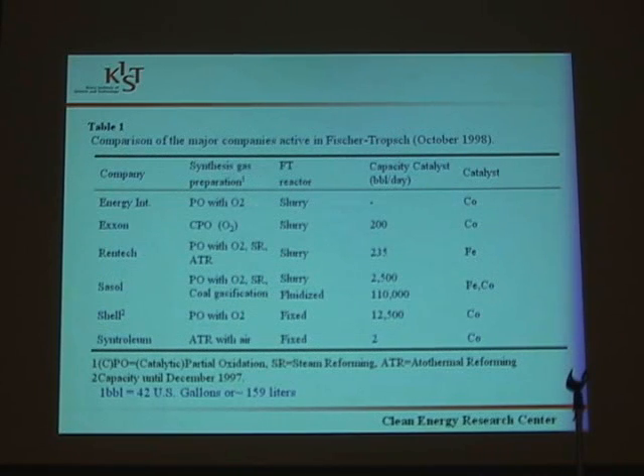Up till now, major companies are already using some catalysts for Fischer-Tropsch synthesis, as given in this table. Energy International is using partial oxidation. They are preparing syngas using partial oxidation with oxygen, using a slurry reactor and a cobalt catalyst. Exxon is using catalytic partial oxidation by oxygen in the slurry reactor and using cobalt as a catalyst.